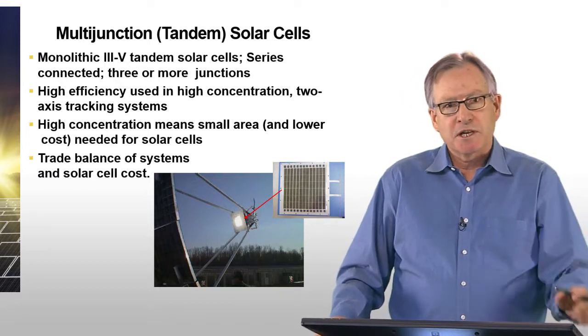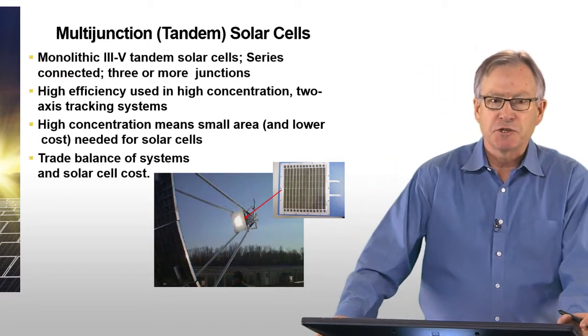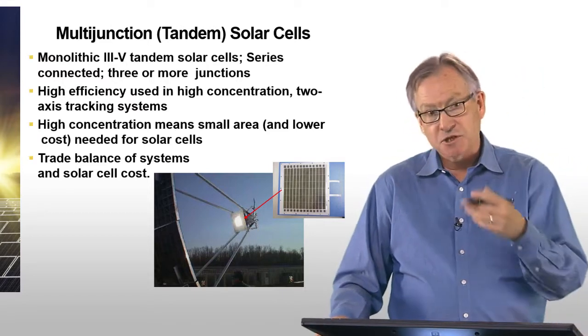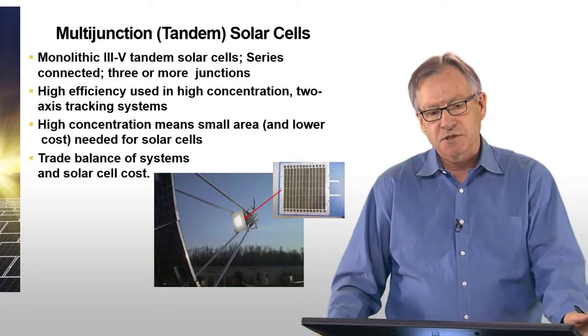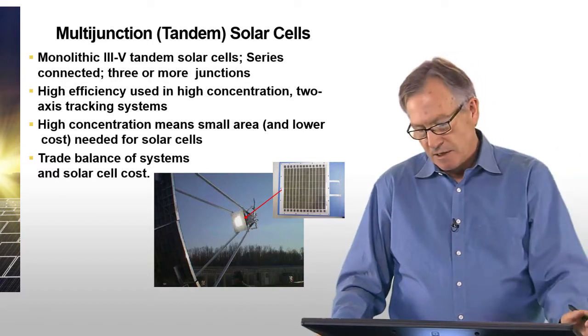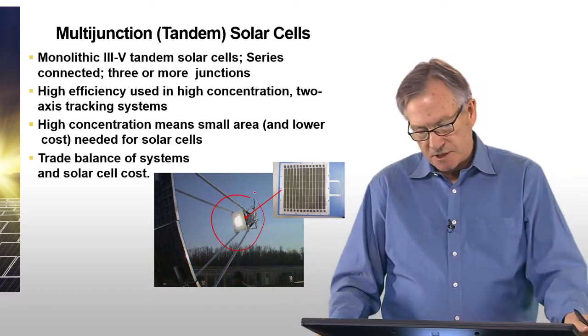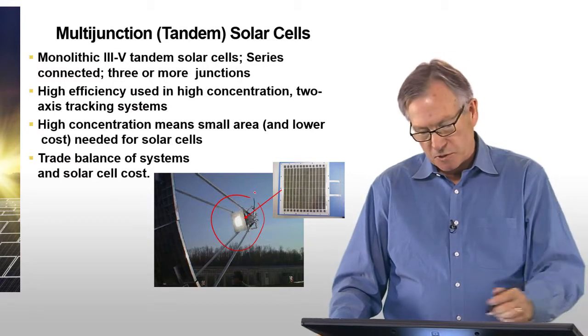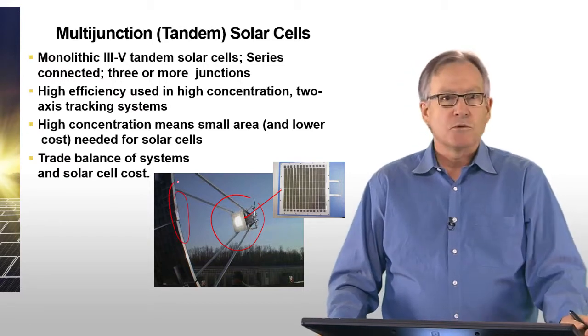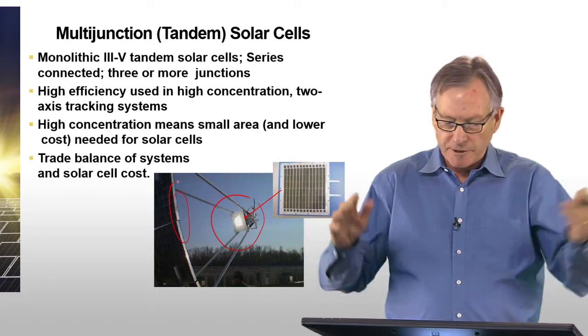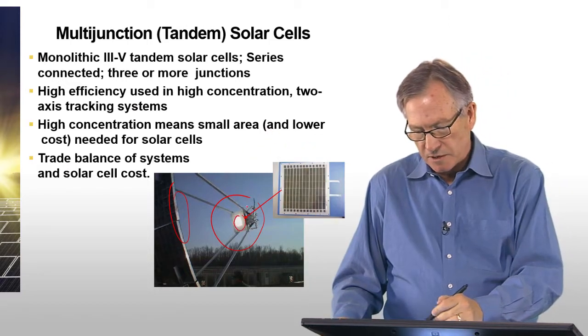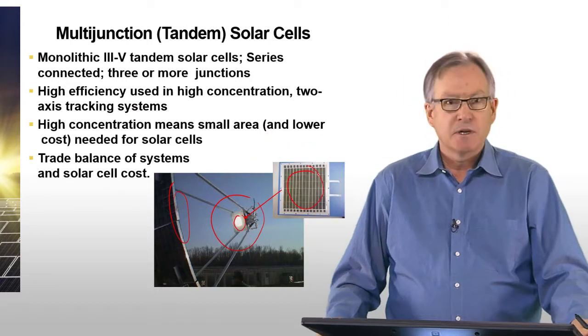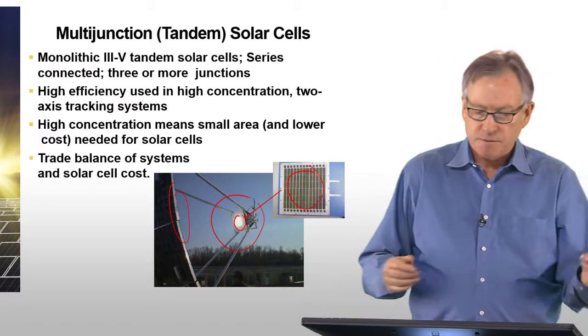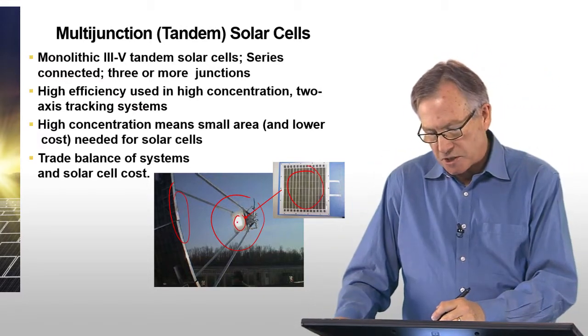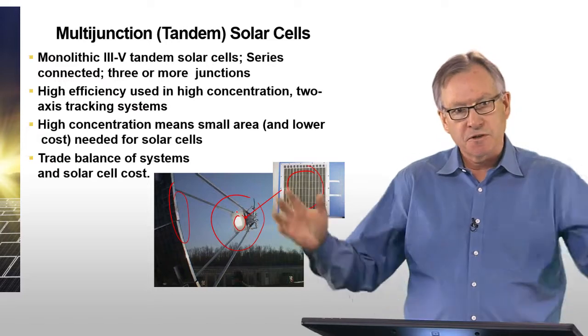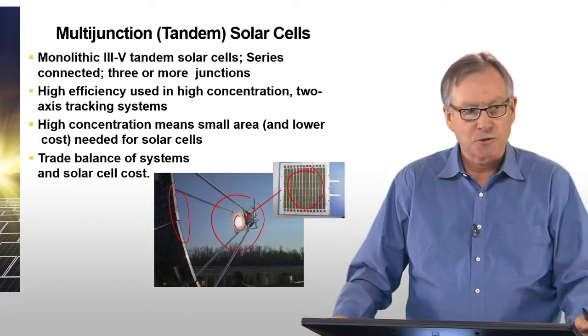For terrestrial applications, the strategy that's being used is to use multi-junction cells in concentrating photovoltaic systems, or CPV for short. This basically illustrates a CPV system. What's shown here is basically a mirror which is concentrating light over a much broader area onto a small array, which is basically shown here, of multi-junction solar cells. And so you have costly but high efficiency cells in a small area, and then you concentrate light from a much larger area.